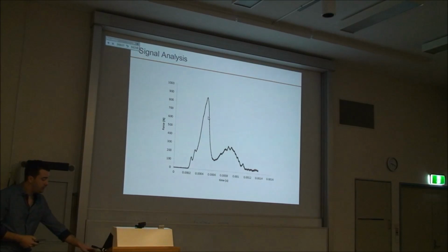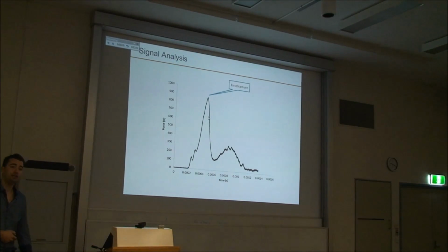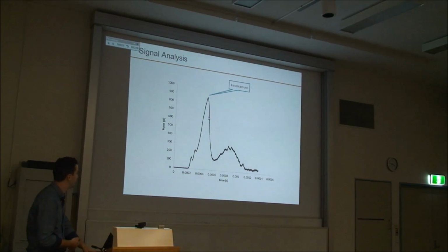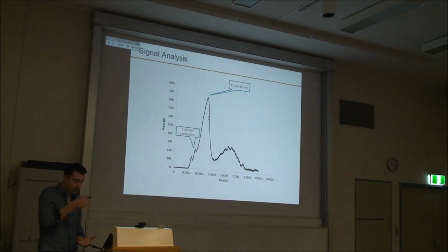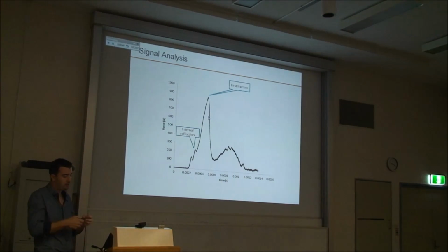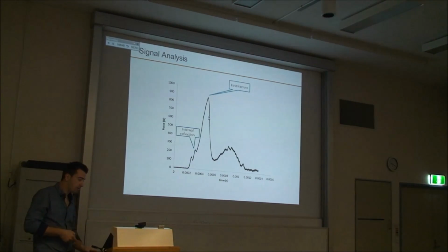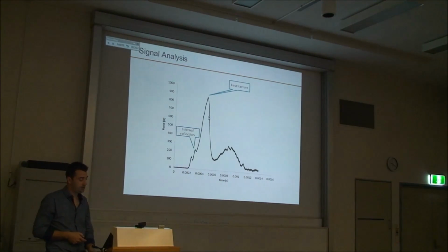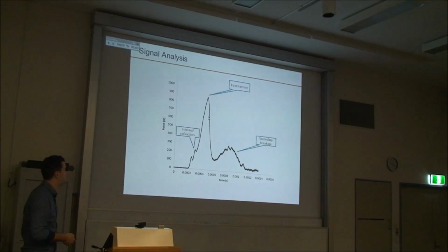So this point is called the first fracture, and it's a mechanical property. It's how much force or strain or stress the particle can sustain before fracture. Here is the internal reflection. That's just when the particle starts to be compressed, the compression wave can actually be reflected within the sample. That's just an artifact of the device, but that doesn't cause any issues. And this is secondary breakage.